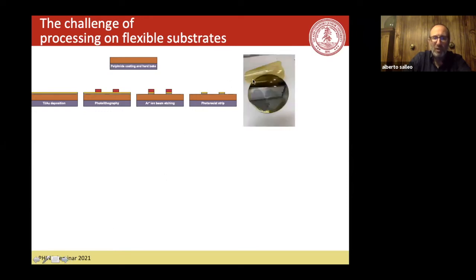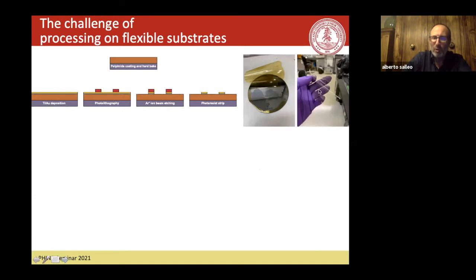Once we peeled the polyimide, this metal had built-in stress, and that stress made it curl. So the first step was to figure out how to make sure the polyimide didn't curl, and that took quite a while, but there's somewhat standard ways of doing that. One is you make this very thin, so it doesn't develop a whole lot of stresses when the metal is deposited on it. And then you use adhesion promoters and all sorts of other tricks to make sure that this then doesn't develop any stresses when you put the metal down. Eventually, we were able to have it so that you could have metal traces without the polyimide curling.